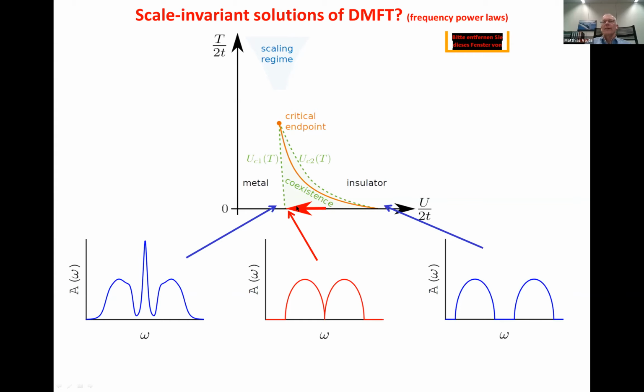Which means the blue solution here sees nothing. And this is why the story I told you has gone unnoticed despite 30 years of DMFT research. Because if you just look at the thermodynamically stable phase, you just follow this blue curve up to UC2, and you don't see any of the physics which I described. You have to decide to study the metastable insulator to see this physics.